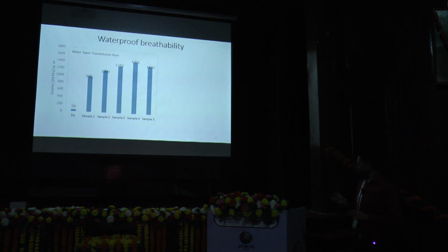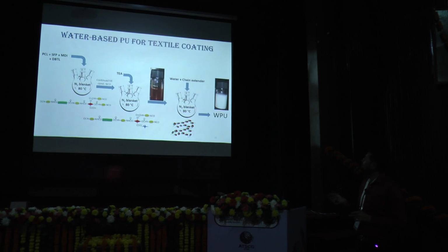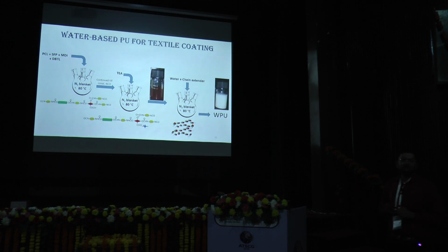So what we have done in our lab, we have prepared a polyurethane by a certain process. This is a patented product and published literature as well. Now there are two problems in polyurethane. One, it is solvent borne, that is, toxic solvent is used, and second, polyurethanes are not functional. So in this work we have targeted both problems. So we have made water-borne polyurethane, so water is used, and second, this polymer itself is antibacterial.